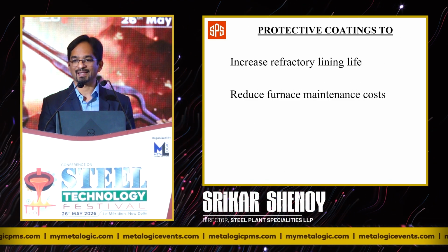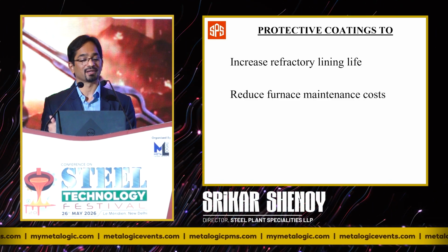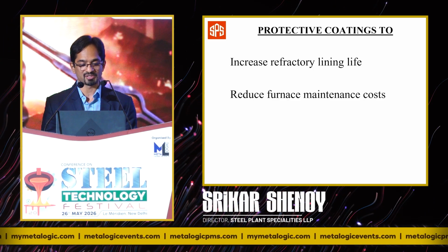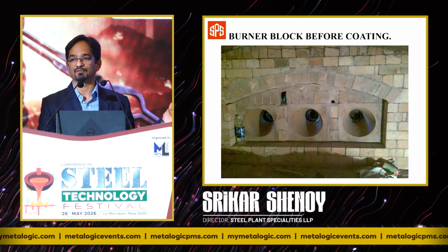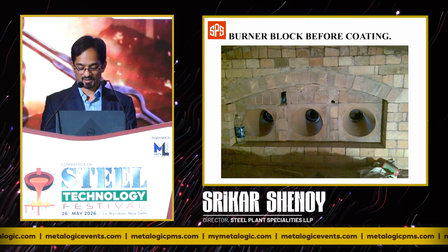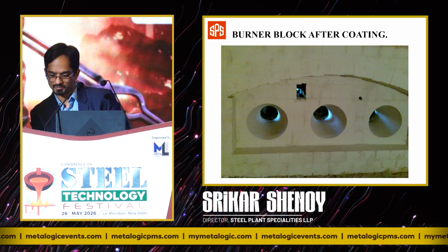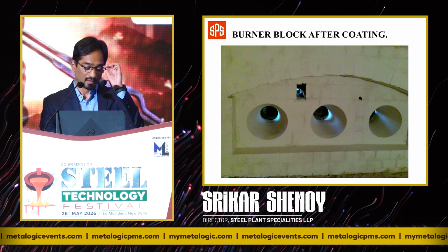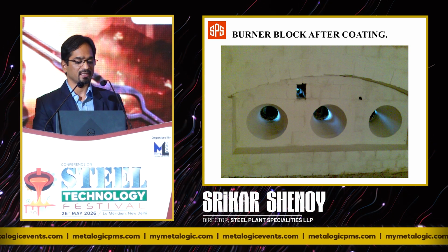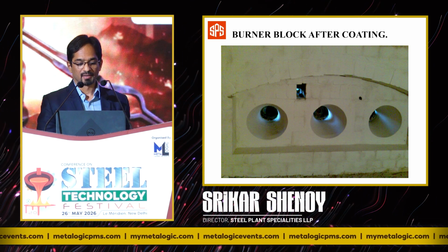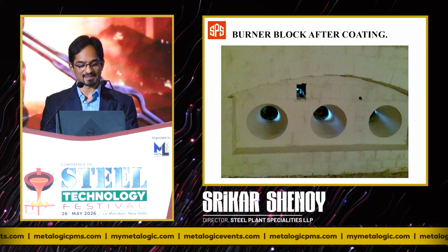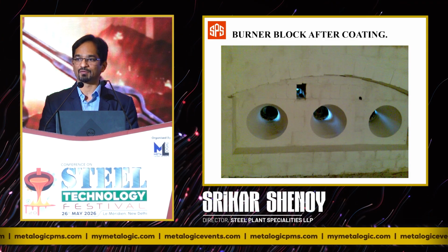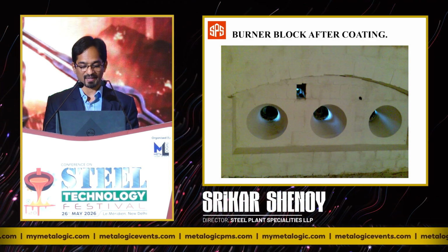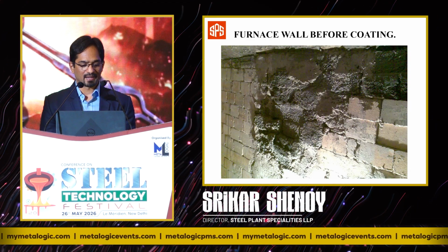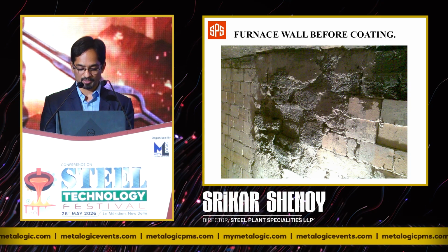Now I quickly move on to the next subject, protective coating for reducing fuel consumption in furnace operations. What you're seeing here is a refractory lining of a furnace. Here is the coated refractory lining. The coating can withstand 1900 degrees Celsius. It reflects the heat back into the furnace, thereby reducing fuel consumption and increasing your refractory lining life. It can be done on a used refractory also, as you see here.